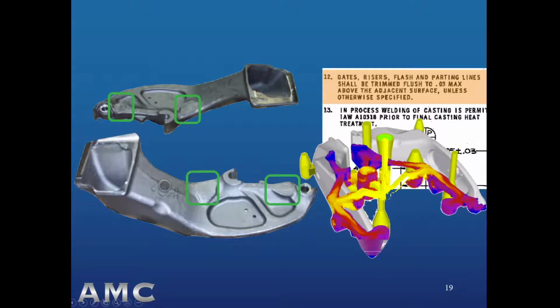And incidentally, here is the parting plane of the mold, top half and bottom half, that you can see clearly is somewhat different than the adjoining smooth surfaces on each side of that parting plane. Well, notes like this help: "Gates, risers, flash, and parting lines shall be trimmed flush to 0.03 of an inch max above the adjacent surface unless otherwise specified." And that's the kind of callout that allows this raised surface here and here.